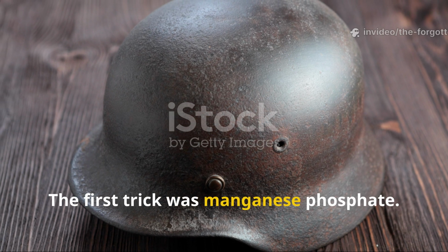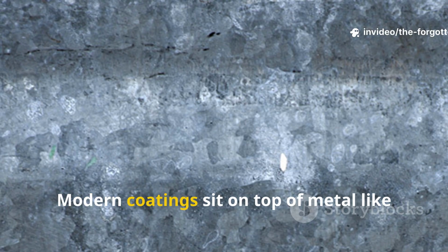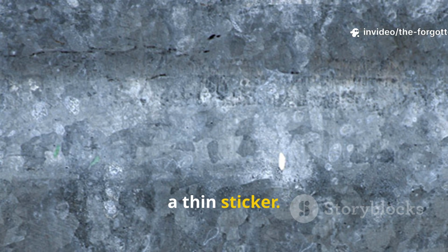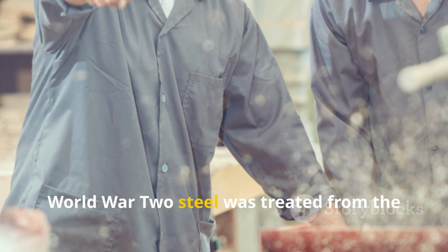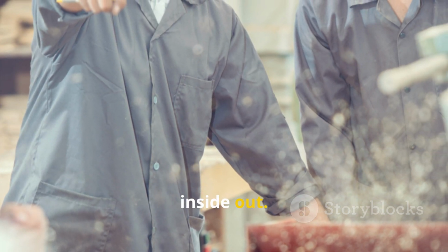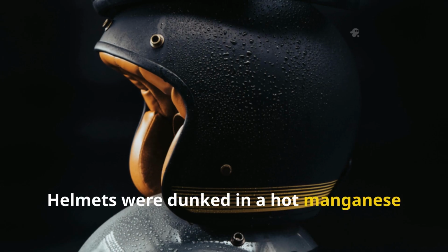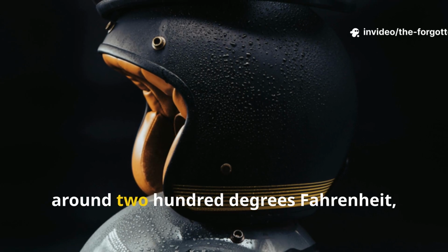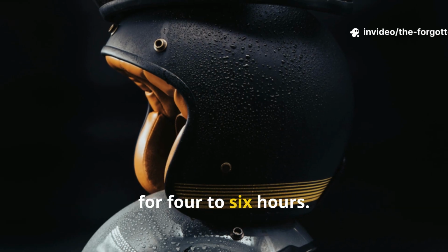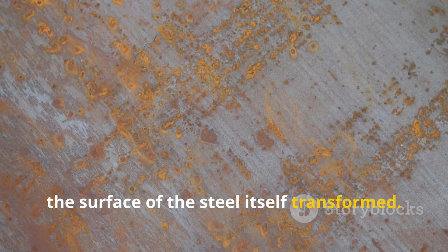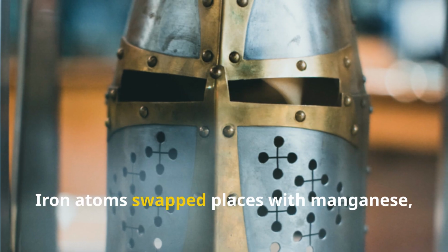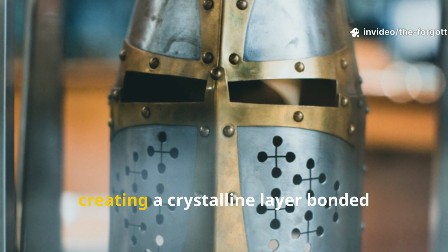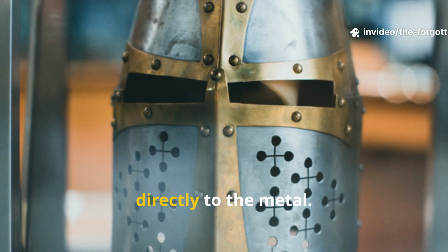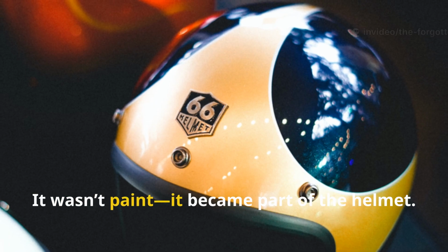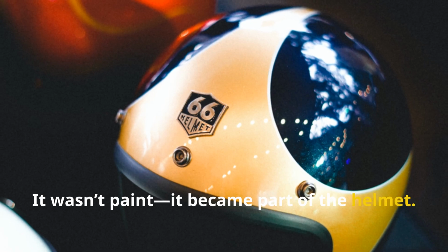The first trick was manganese phosphate. Modern coatings sit on top of metal like a thin sticker. World War II steel was treated from the inside out. Helmets were dunked in a hot manganese phosphate bath around 200 degrees Fahrenheit for 4 to 6 hours. During this time, the surface of the steel itself transformed. Iron atoms swapped places with manganese, creating a crystalline layer bonded directly to the metal. It wasn't paint, it became part of the helmet.